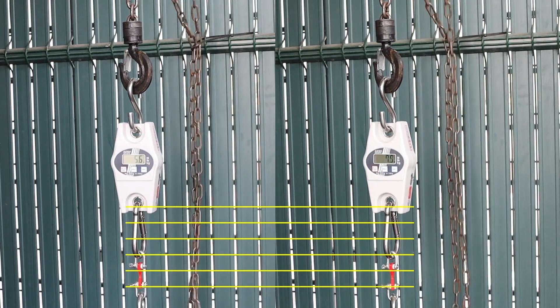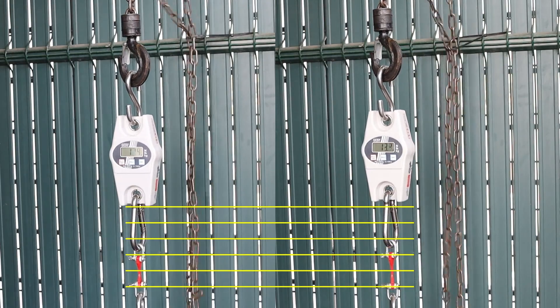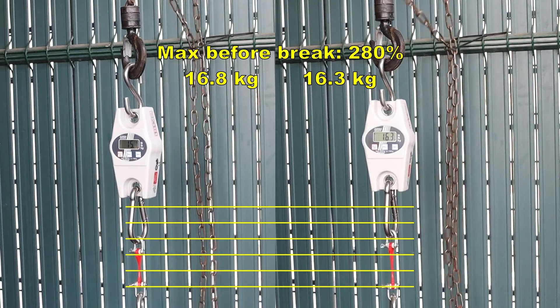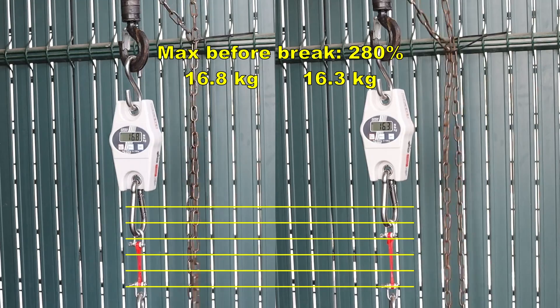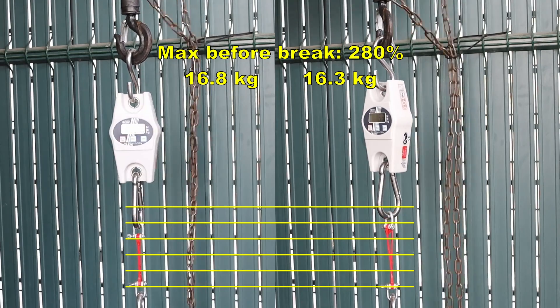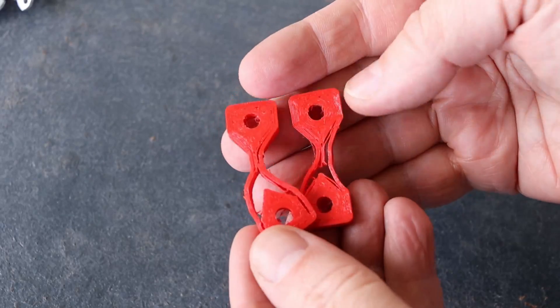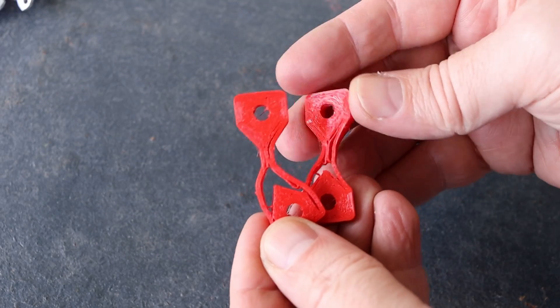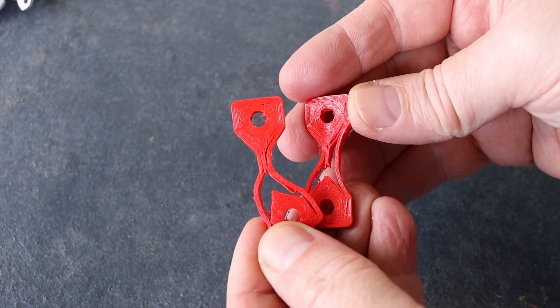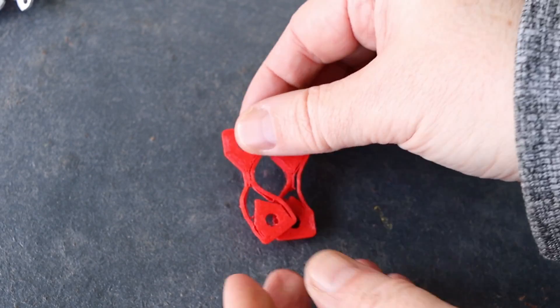The tensile or pulling test with horizontally printed objects. The first failure I noticed at 280% and actually it was the delamination between the walls of the object.